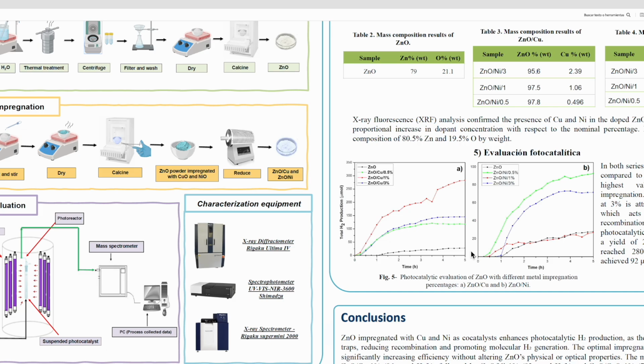Once we obtained this material, we moved on to the last step, which was the evaluation, in which we could see that precisely in image A, the one that generated the most hydrogen was the zinc oxide with copper at 1%. These results are interesting because, as our hypothesis suggests, by adding this transition metal as a co-catalyst, the photocatalytic production would improve, and indeed, that's what happens. All the samples at 0.5, 1, and 3% surpass the hydrogen production of pure zinc oxide.